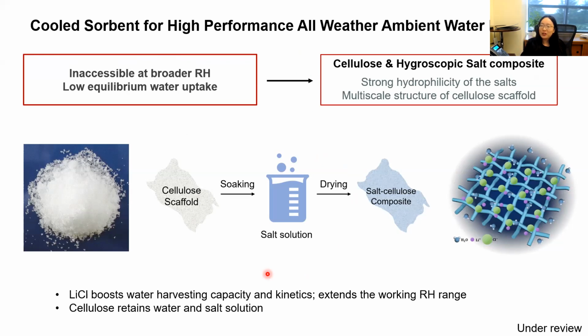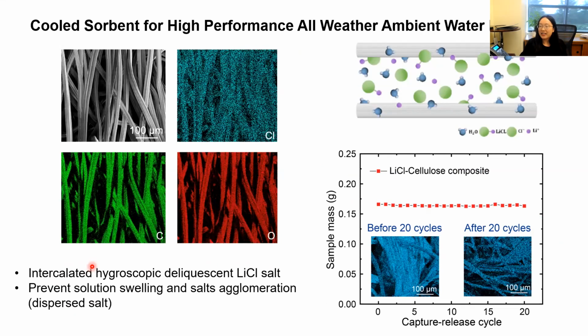So we were trying to use a salt that's quite good at absorption, to boost the water harvesting capacity as well as the kinetics, so that the working range of relative humidity can be extended. And we hope that the cellulose can provide the mechanical support to retain the water and the salt solution. Then we used SEM and element mapping to look at what's really happening inside. This shows nicely that the salt indeed gets intercalated among the fibers. And by doing a cycle performance test to look at the sample mass, the same set of cellulose fibers can well confine the salt and the salt solution, very well disperse the salt, and prevent salt agglomeration.